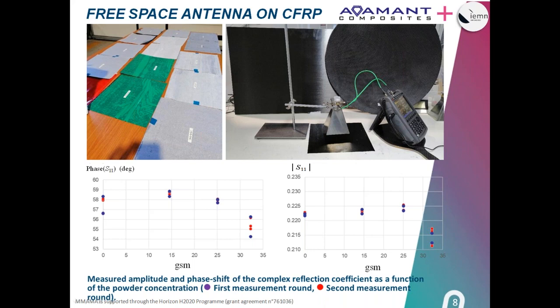Then again, on the prepreg samples, we did some measurements with the free space antenna system developed by IEMN. And here you can see some results to show, on the same prepreg type, how the different amount of the dopant affects the response that we get. And at the end, we can correlate this with the property under investigation. This time, it was the electrical conductivity. This test also helped us optimize this system to further integrate it into our roll-to-roll pilot line, which we'll see later on in this presentation.